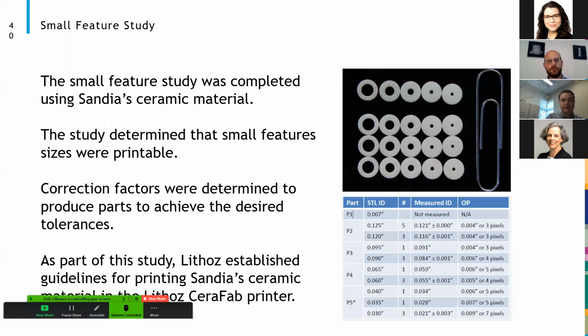On the other end of the spectrum, we did a small component study. So very small ID features was the focus of this study. We were looking for clearance holes ranging from 30 thousandths of an inch all the way through 1/8 of an inch in diameter. As you can see in the table on the bottom right, we did determine the geometry is printable. However, we'll need further characterization to get the exact desired tolerance, and we'll talk about this later.